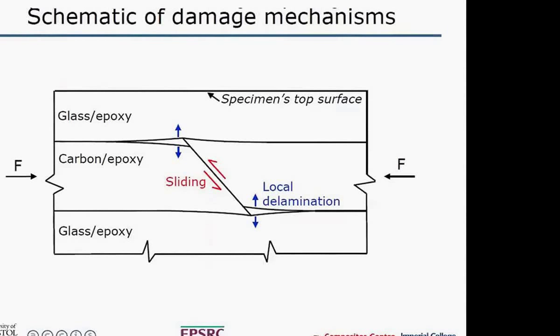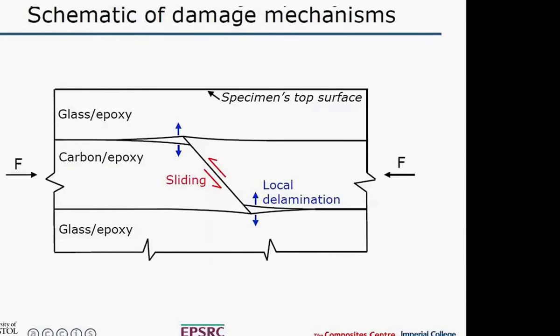Looking at it schematically, with this angled crack, when you've got sliding across that angled crack, that pushes the composite apart here. You get this little bit of delamination, which is a mixed mode delamination. That allows some relative motion here, which allows the strain to change, even though the load is not changing very much. As this fragmentation progresses, the carbon is still carrying about the same load as it was when it started to fragment, but it can strain because this mechanism allows relative motion while still carrying the load. So I think it's quite interesting to get to the bottom of this and how it behaves.